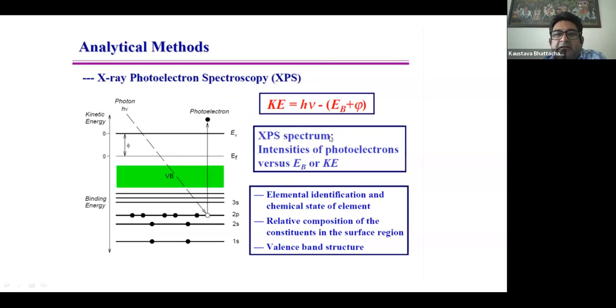So, as we have found out the binding energy of the system, what we can identify from these X-ray photoelectrons is the particular element, because every element has its own particular energy of electron being ejected from the shell. We can understand the relative composition of the surface, and we can get the valence band structure. Basically what we get is the density of states related to that element. By density of states, we can get the energy of the particular orbital of each element within the energy limit of the source. Whatever source we have utilized, within the regime of that source energy, we can find almost all the band structures or orbital structures.